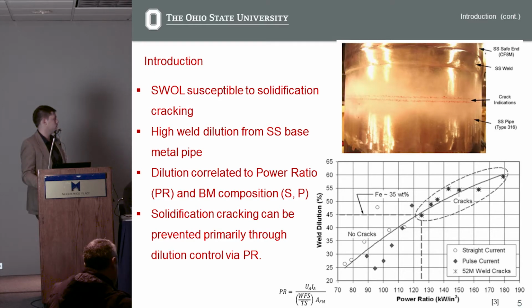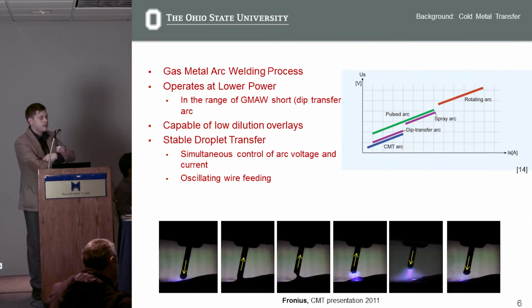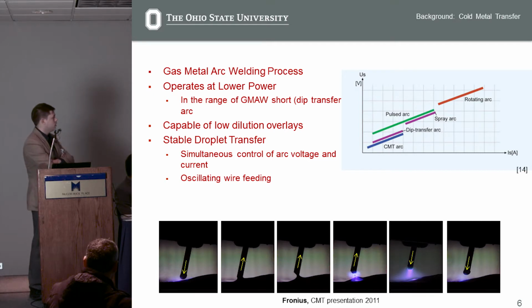And this weld dilution has also been correlated with high power ratio with the hot and cold wire gas tungsten arc overlay process that they had been using to deposit this metal. So in an effort to solve the solidification problem to our structural weld overlay, we are investigating the CMT, the cold metal transfer process by Fronius, to provide a low input structural weld overlay deposition process.